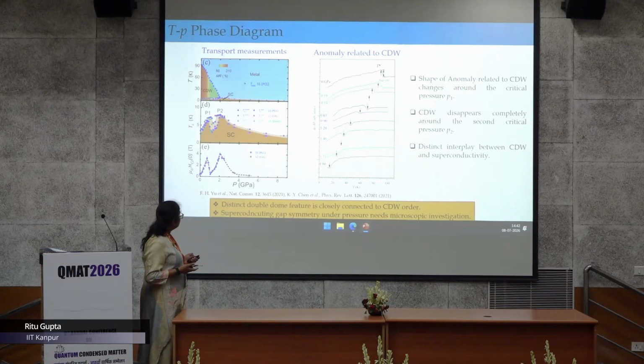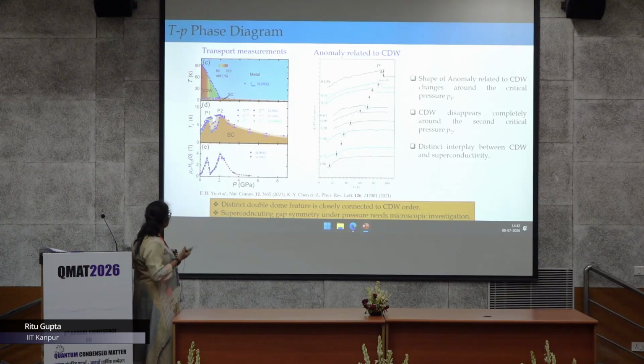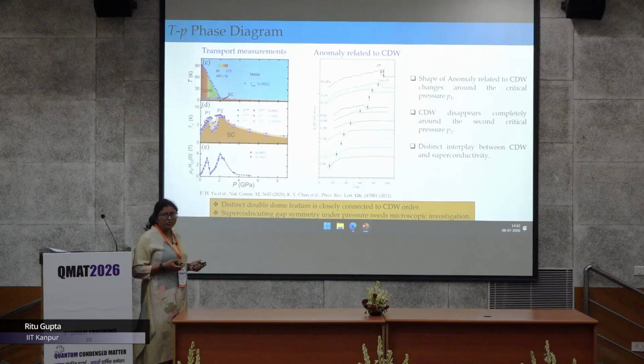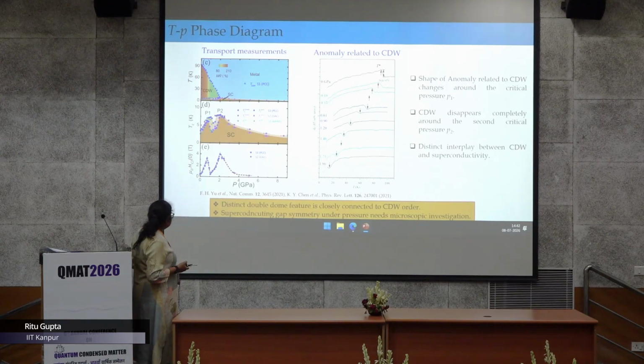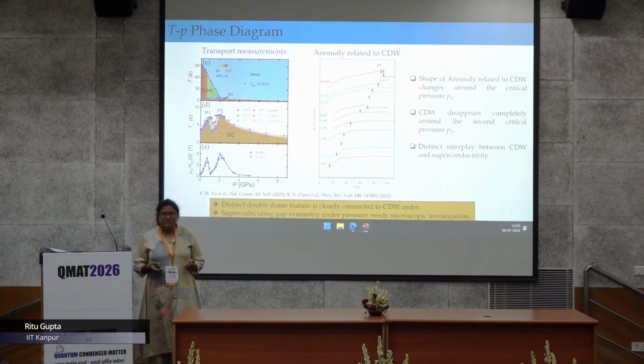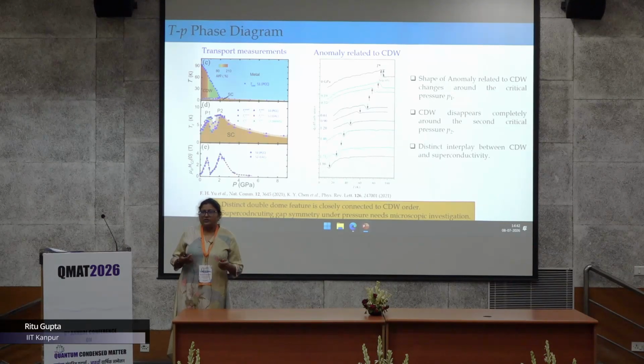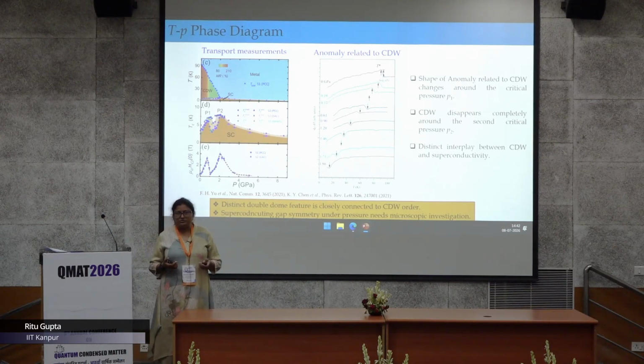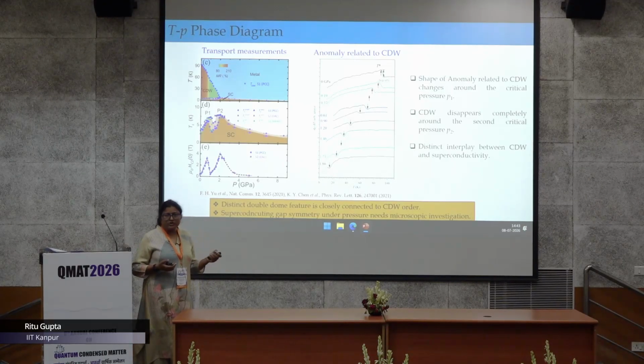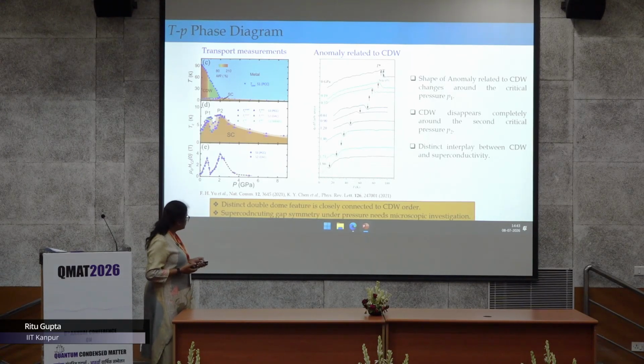But what happens when you apply pressure? If you look at the existing phase diagram, this charge density wave phase is suppressed with pressure, and it completely disappears around a critical pressure of about 2 GPa. And we see a high value of Tc, about 8 Kelvin, around this critical pressure, which is understood because when the charge density wave phase is suppressed, the charge carriers which were depleted because of it are now available to participate in the superconductivity phenomena.